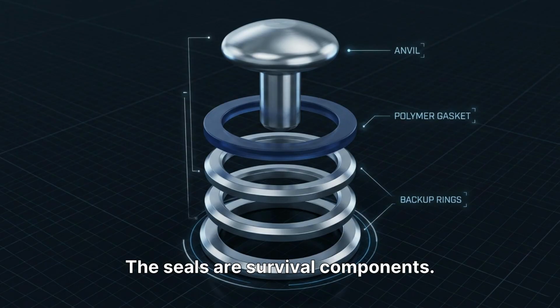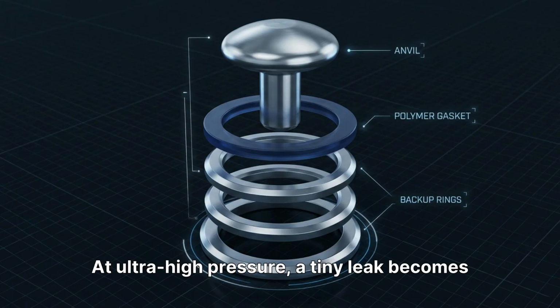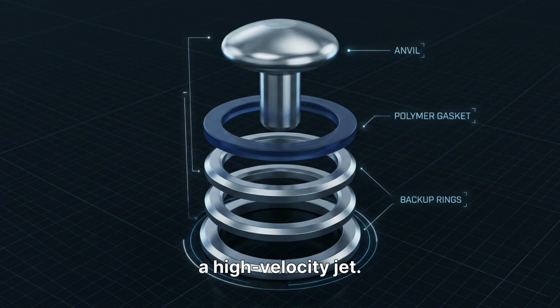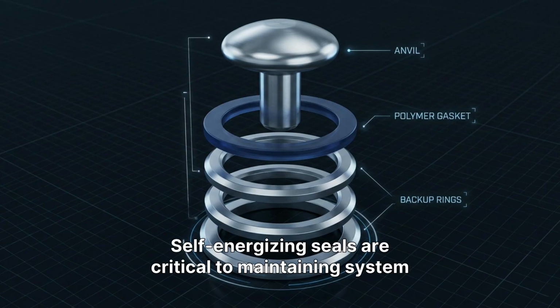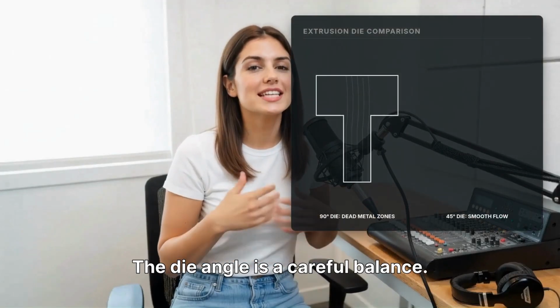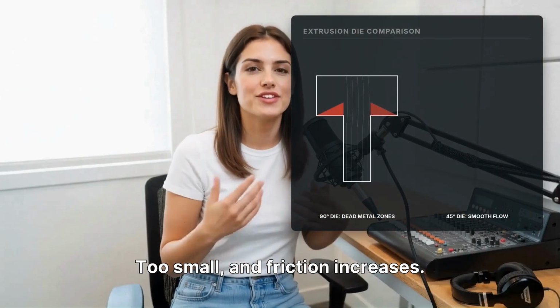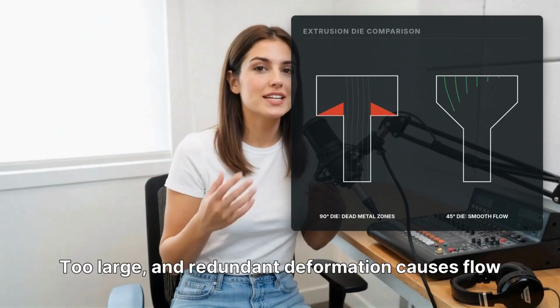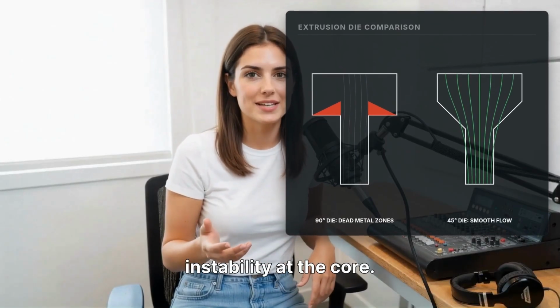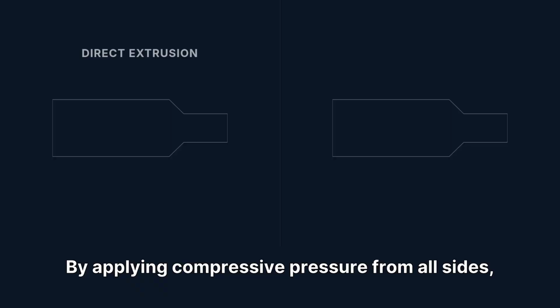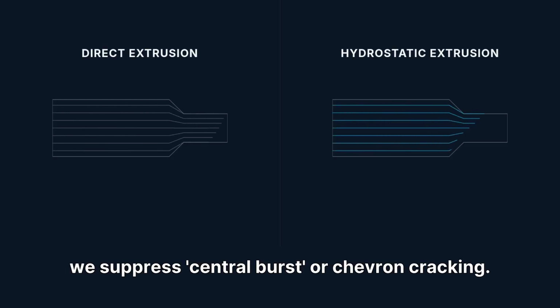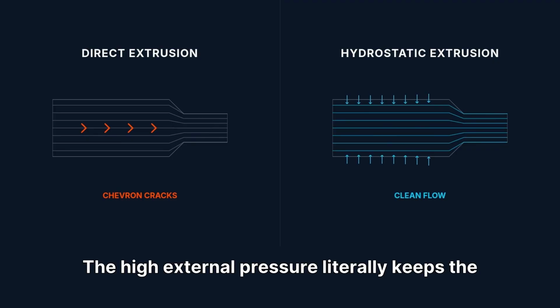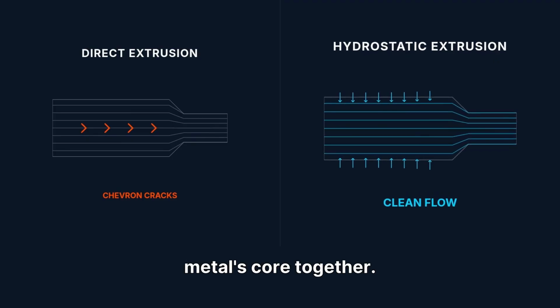The seals are survival components. At ultra-high pressure, a tiny leak becomes a high-velocity jet. Self-energizing seals are critical to maintaining system integrity. The die angle is a careful balance. Too small and friction increases. Too large and redundant deformation causes flow instability at the core. By applying compressive pressure from all sides, we suppress central burst or chevron cracking. The high external pressure literally keeps the metal's core together.